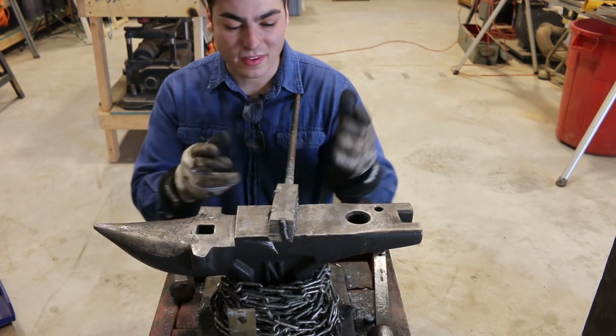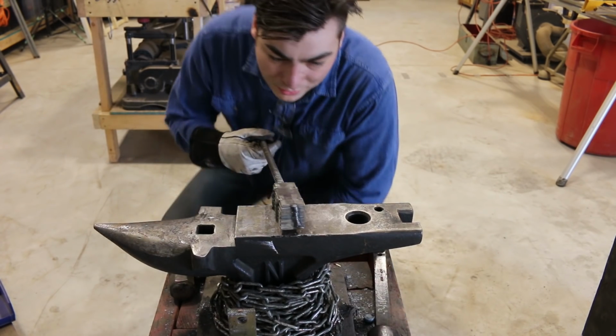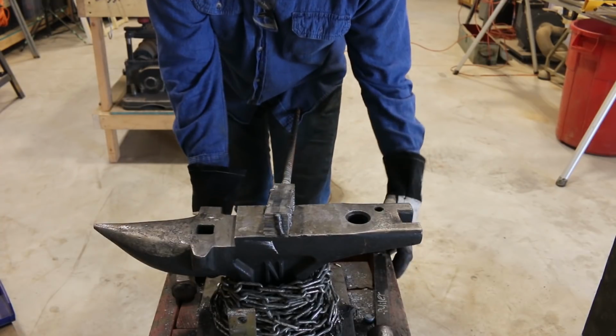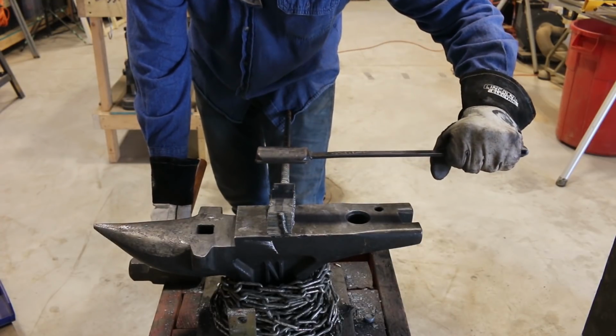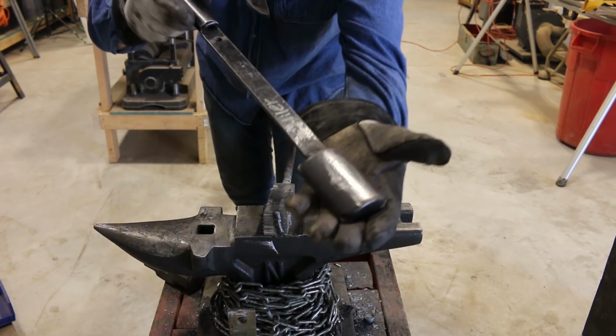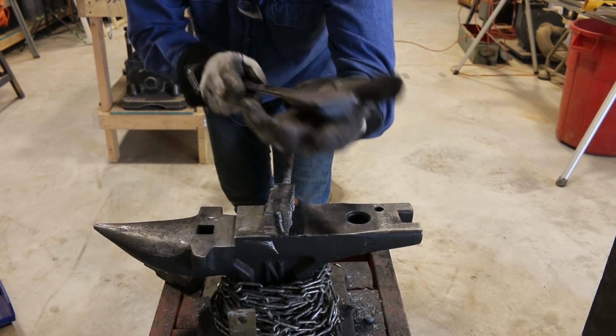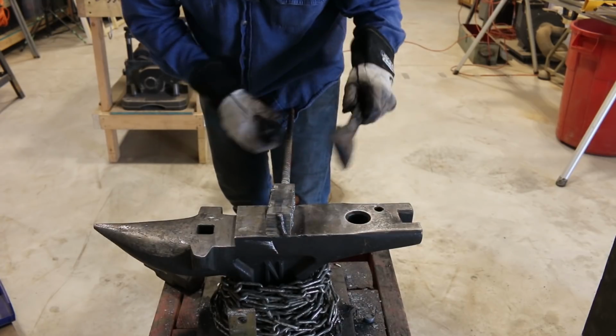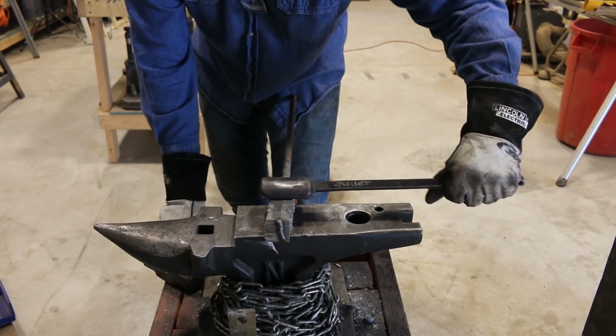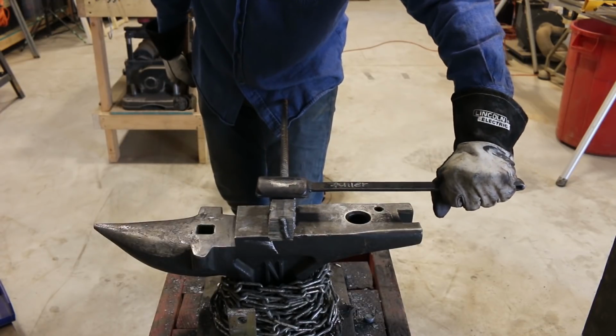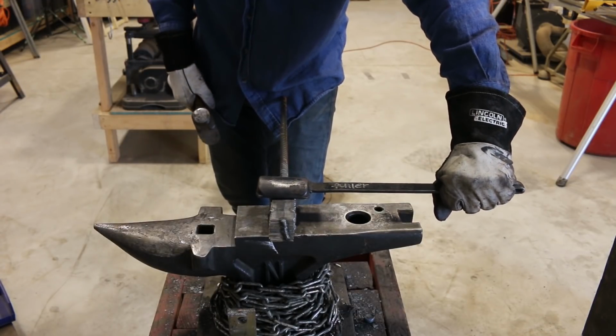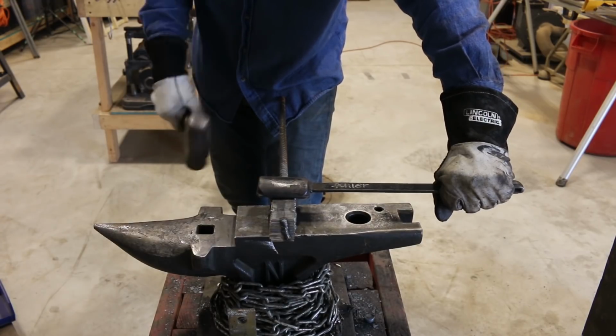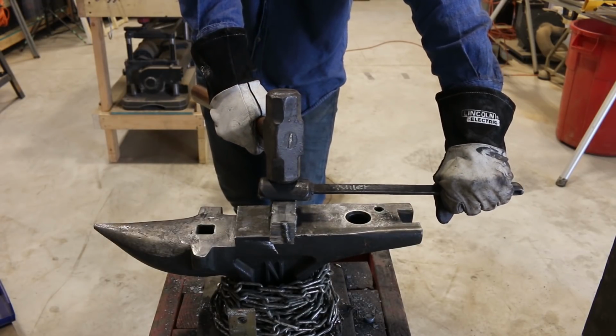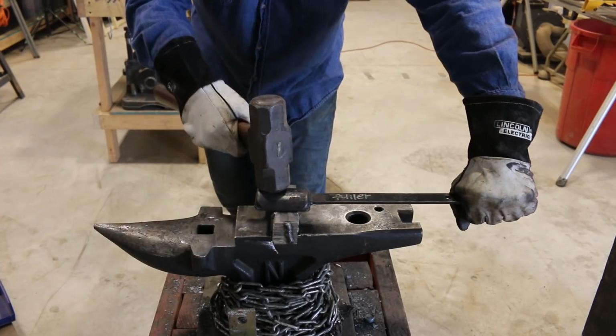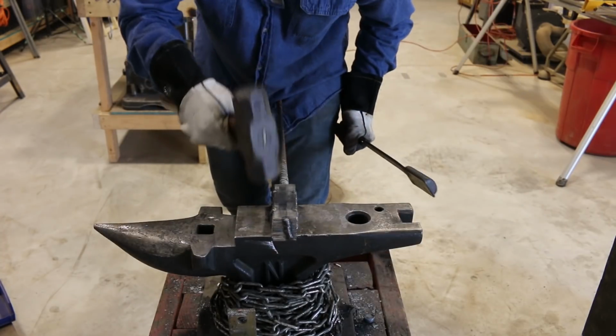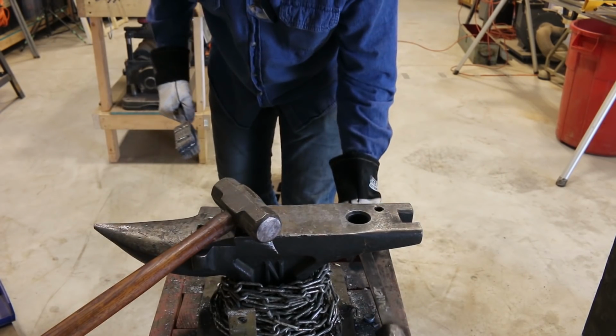Now, if you're dead set on using thicker steel or whatever, one thing that I use to help with that is a flatter. So this is just like a flattening tool. It's also got a little bit of a fuller on one side. I use this in my hydraulic press. I also use it to flatten steel that's been beaten up too much. But it's really nice for setting billets because you can set a much larger portion than the width of your hammer. So with a few solid hits, I could set this whole billet rather than zigzagging back and forth in order to get the whole face.